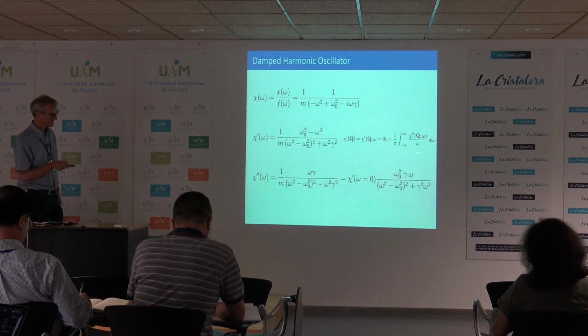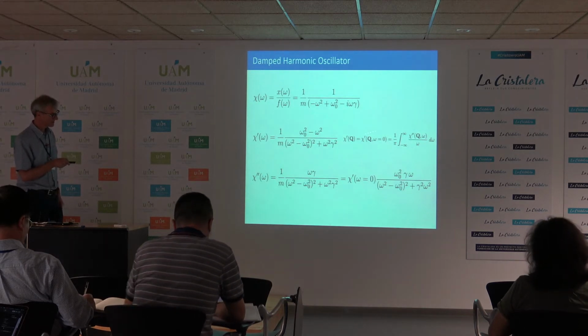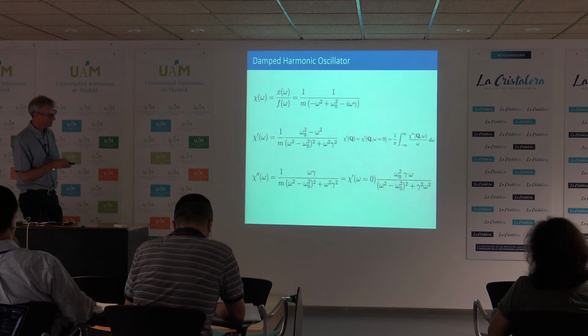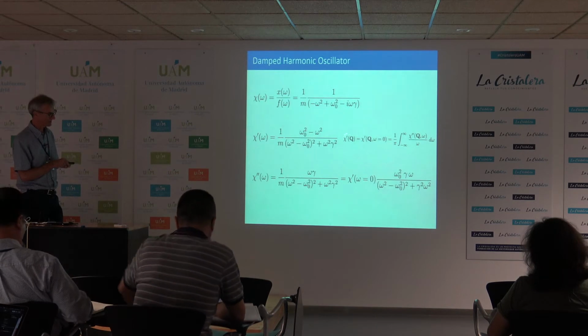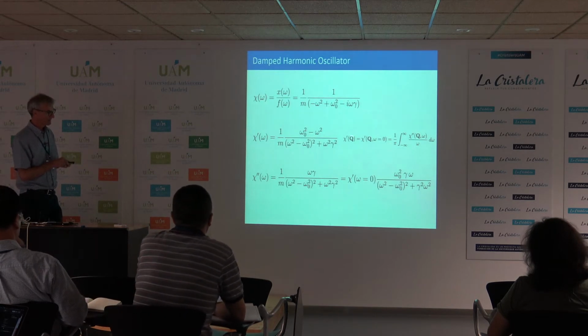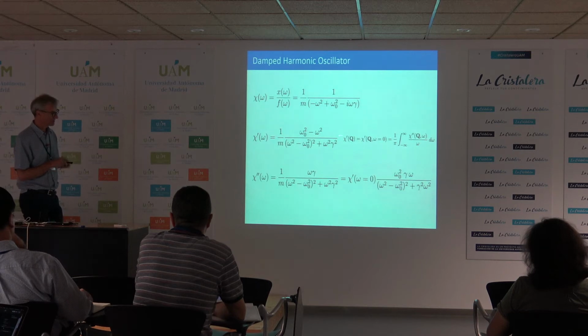Another useful thing in neutron scattering is the Kramers-Kronig relation, which relates what we measure with neutrons, the imaginary part, to the real part, which often comes in handy. In the limit of zero Q, this would just become the static susceptibility. But if one looks at fluctuations, just thermally induced fluctuations, for example, when you measure a correlation length, it actually is the real part that's relevant.